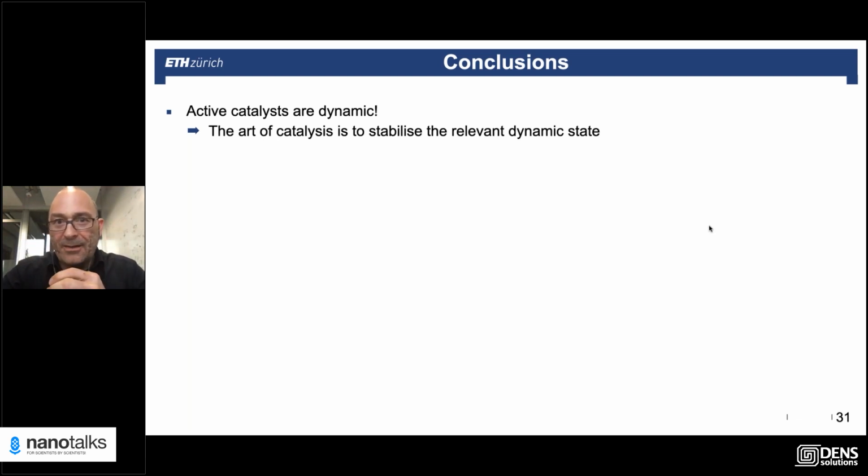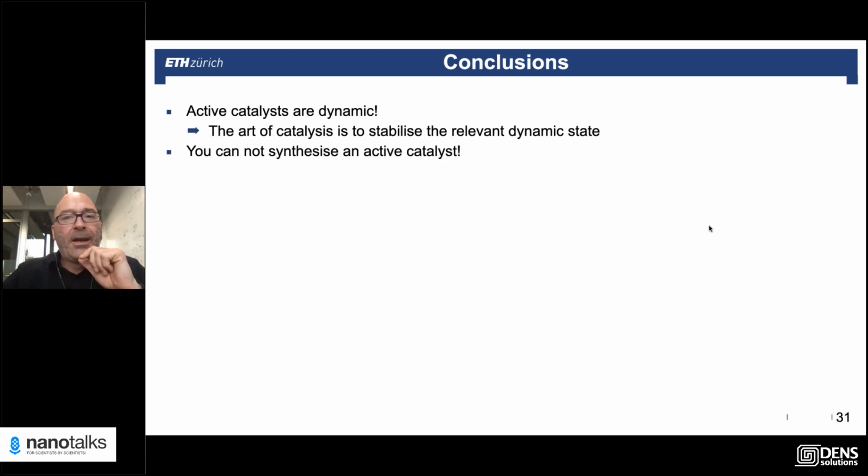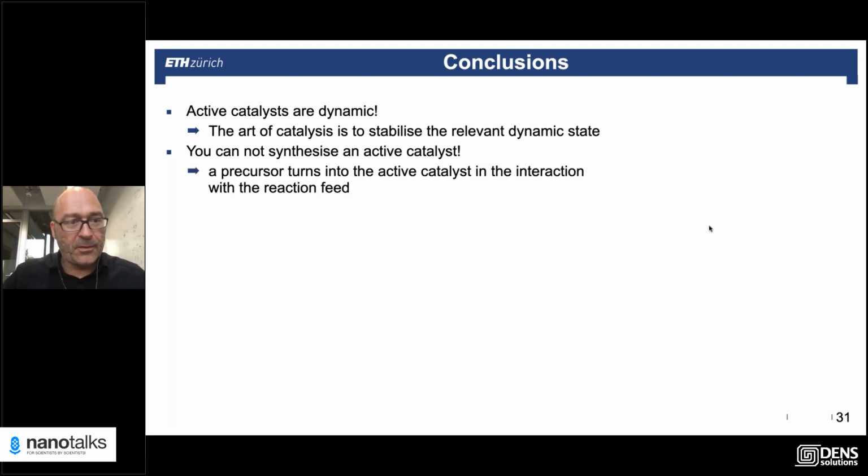That's the art of catalysis development, to stabilize the relevant dynamic state. And one thing that is wrong is that you cannot synthesize a catalyst. What you synthesize is a precursor. Under reaction conditions, the reaction environment transforms the precursor to an active state, but you cannot say, I designed this catalyst or I synthesized this catalyst. That would just be wrong. So as I say here, the precursor turns into the active catalyst in the interaction with the reaction feed.